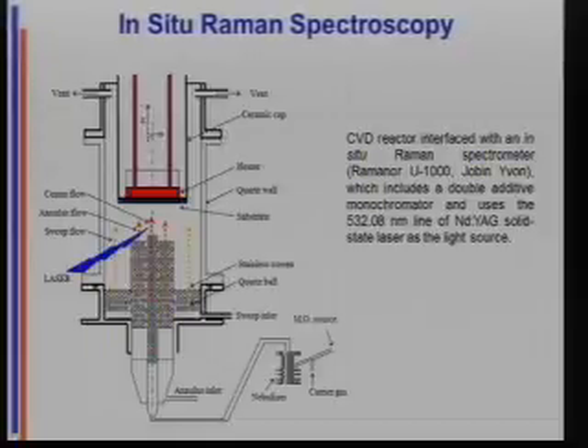If you think about the temperature gradient that comes from the heater, by moving this up and down and keeping the laser position constant, you can temperature profile the gas phase species inside the reactor while you're growing film, by taking the Raman spectrum of what's in the middle. This is really cool because if you think about CVD, you have a heated surface here, you're growing at the surface, but there's a temperature gradient that starts, say, from 400 here going on up. And so part of your CVD chemistry always takes place in the gas phase because the molecule is being heated as it approaches. So it's a mixture of gas phase chemistry and gas surface chemistry. And so this reactor allows us to look in situ at the gas phase part of the chemistry during the reaction. And what do we see?